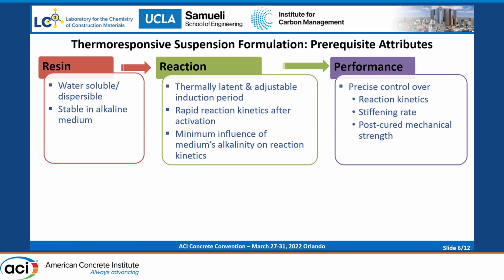And coming to the reaction kinetics, they should be thermally latent and should have a good induction period. We don't want these resins to react until we trigger it. And once we trigger it, once it reaches the activation temperature, it should have very rapid reaction kinetics. Then only we'll be achieving that rapid fluid to solid transition. And the reaction kinetics should not be affected by the alkalinity of the suspending medium.